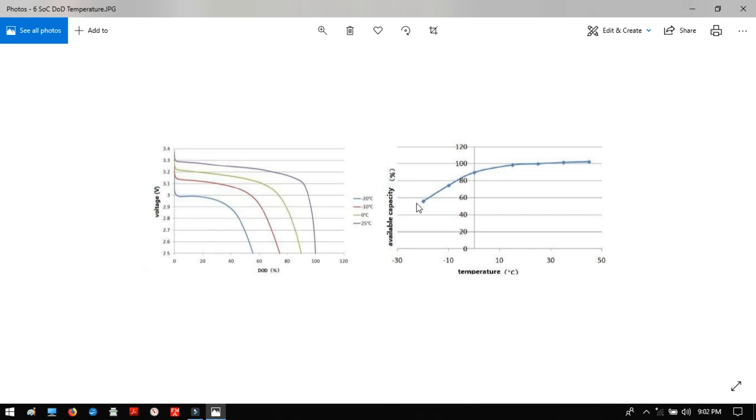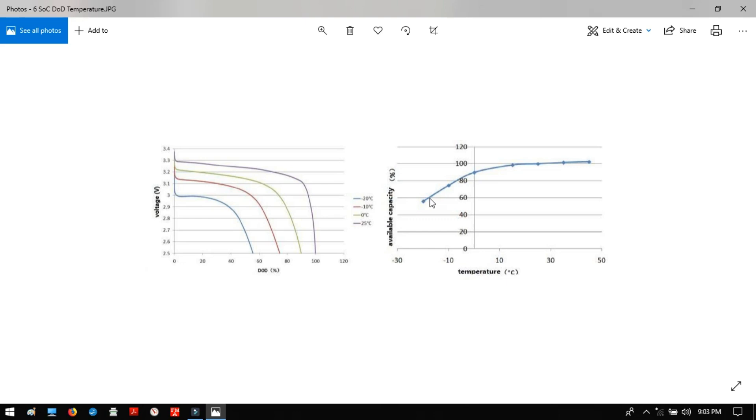And you can see that here, this voltage drop is lower at this colder temperature, minus 20. State of charge, drop, drop, drop. This also shows you here the capacity of lower usable capacity. So when you're down to like 60% here, close to minus 15 Celsius, that 20 amp hour cell, that was 20 amp hours up here at 25 Celsius, by timing it down here, it was only a 12 amp hour cell. That's all the capacity it has in amp hours.